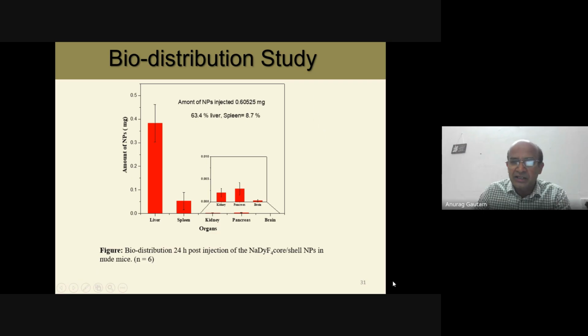And mostly, as you know, this all goes into the reticuloendothelial system. The RES system absorbs most of the particles. So we still have to design something that can steal from the RES system, because it is the main one to absorb. We have designed some model or some surface coating that can evade the RES system. Mostly at the moment PEG is still the best. PEG can evade the RES system. If you coat the particle with PEG, they can go more to other parts of the body. But here with this polymer, we are able to get very little, even very little in the brain. Almost nothing is there, because these particles are bigger in size, very hard to cross the blood-brain barrier. But mostly the liver, anything goes, we see it almost immediately taken up by the RES system, the reticuloendothelial system. So you can see here the liver is taking 63.4%, and the spleen is 6.7%, and the rest is in other parts of the body. If you coat with PEG, they will evade this RES system and can go to other parts of the body.